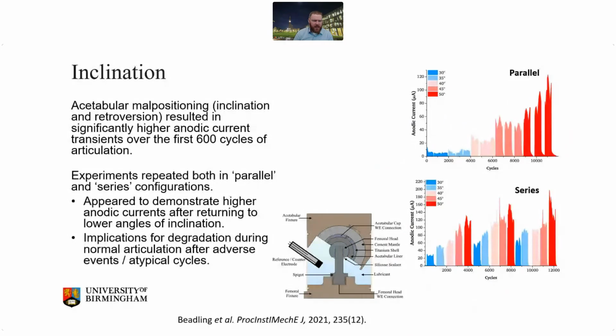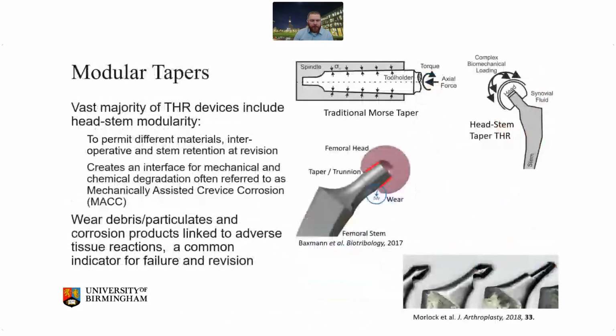So what that suggested was that when you change your articulation path, or when you change the profile, you change the area of the surface that you're depassivating, and the resultant degradation is higher going forward. So that speaks to the importance of switching profiles and looking at daily living routines, or the day in the life of the patient, when you're doing this, to get a full idea of the degradation that's occurring, as opposed to just articulating over a single profile.